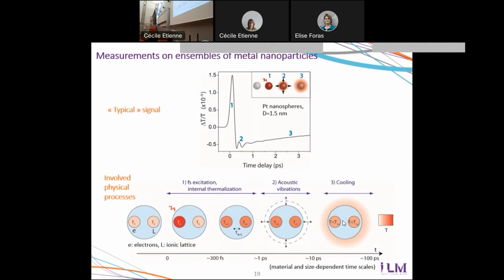Here is an example of the signals that we can obtain for metal nanoparticles. This one was acquired for very small nanoparticles made of platinum, 1.5 nanometer diameter. We show it because it's a nice example of the measurement. It's a time-resolved signal, as I've just described. Here you can see relative transmission changes, and here the delay between the pump and probe beams. At delays before 0, the system is probed before its excitation, so there is no signal.